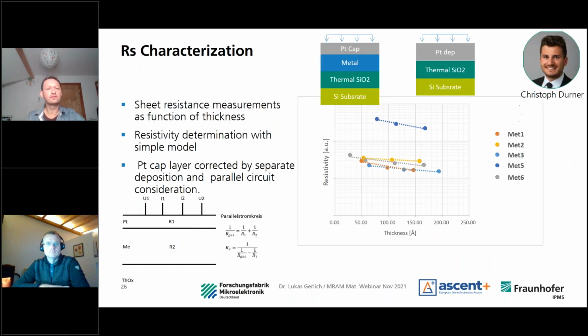Of course, for characterization of a material, the resistance is very important, and this can be done by the same systematic. So you see the different thicknesses. You have a top layer. You determine a resistivity model by this. You can extrapolate, and you can see what would be the thickness. Interpolate or extrapolate, what's the resistance here? And in this case, we also have to calculate the platinum cap and calculate this out with a parallel circuit consideration.